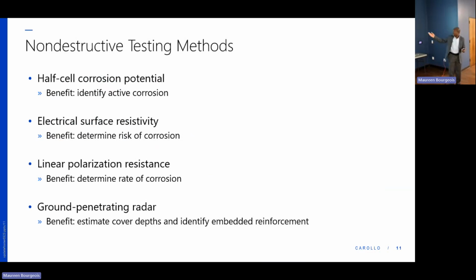And then finally, it identifies the embedded reinforcing and also the cover depth. Now, the cover depth is the face of the reinforcing to the face of the concrete. So that's the cover. Typically, we want to see a minimum of 2 inches on structures such as this in a water wastewater environment, because you want to protect the steel, so you need enough concrete to do that. And we'll get into that in some of the testing methods. And so the penetrating radar will help us estimate this cover embedment depth when we use that equipment.